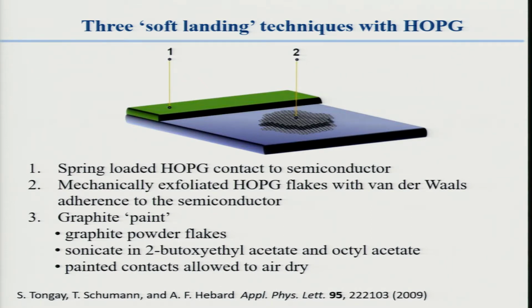So why did we become interested in it? It was because in this process of Schottky barriers, we accidentally made them. And it's one nice thing about being an experimentalist that you can be in the lab and just try something out. What we did was we took some graphite, exfoliated it, and pressed it against a semiconductor. And immediately saw, when we made contacts to it, a diode. And so if it works for graphite, and you know that the first layer of graphite is graphene, it should work for graphene, and it did work for graphene.